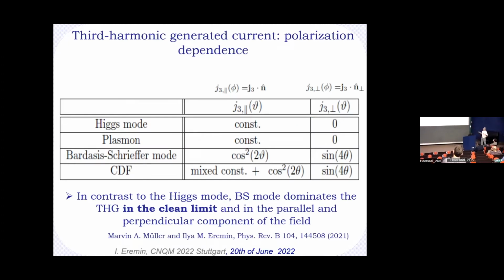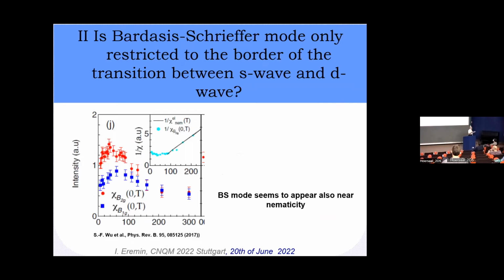And in order to do so, we also computed the expected polarization dependence of this Bardasis-Schrieffer mode in the parallel and perpendicular components of the third harmonic generation current. And you can clearly identify the particular dependence, which is very different from the charge density fluctuations and also from the Higgs mode. Now, you say, okay, so you learn something about the Bardasis-Schrieffer mode, very nice, but